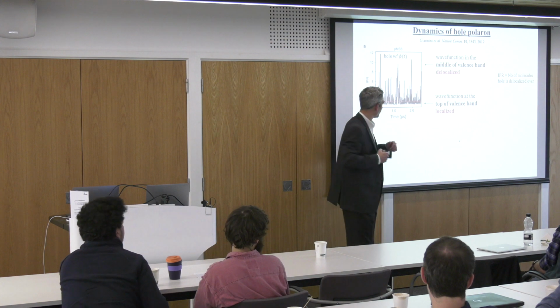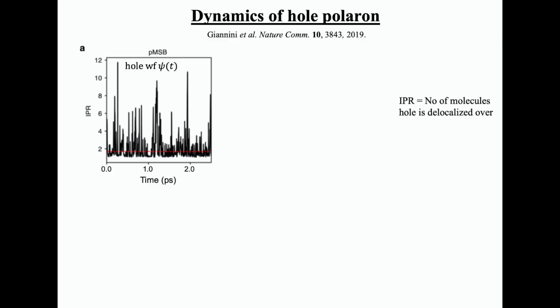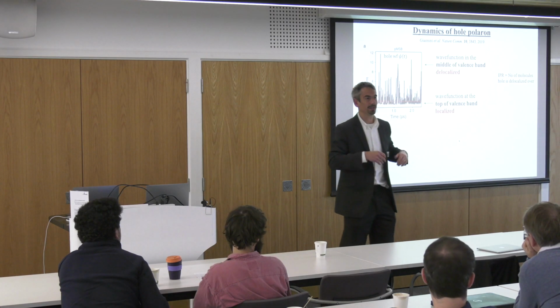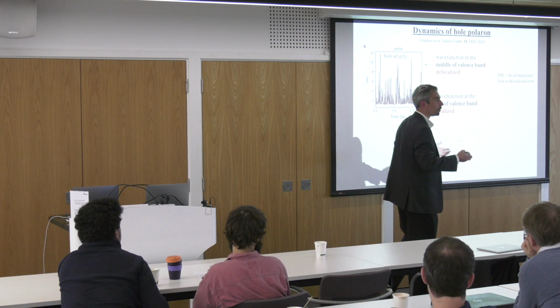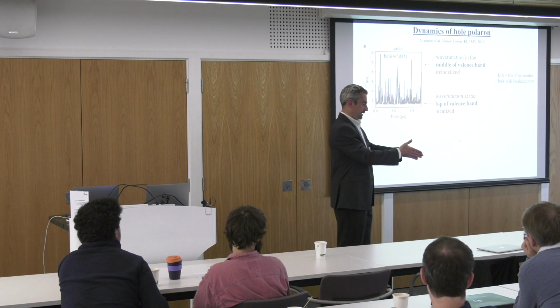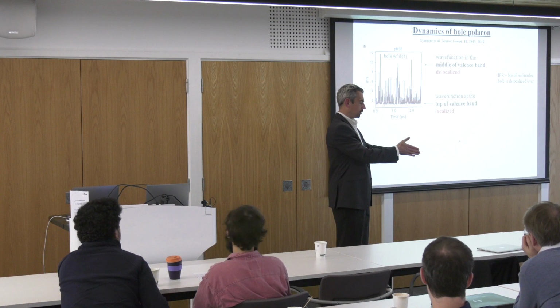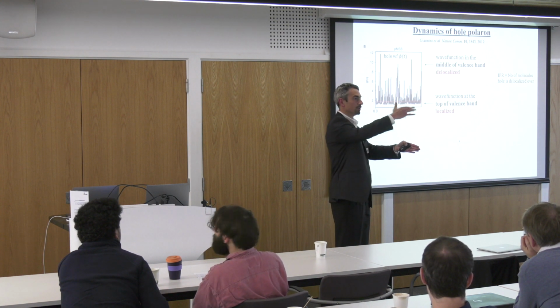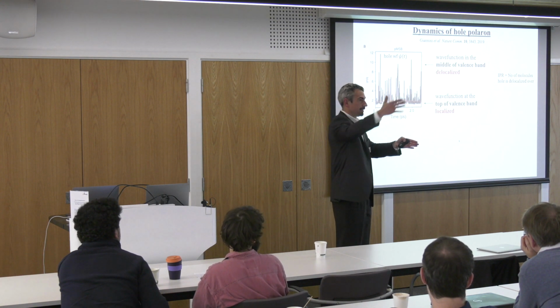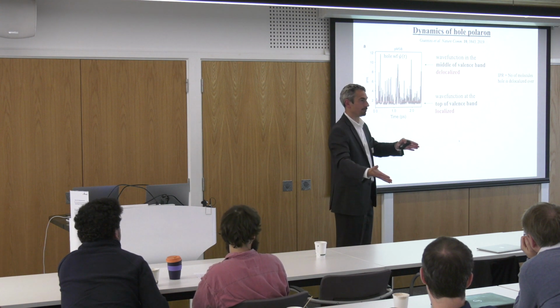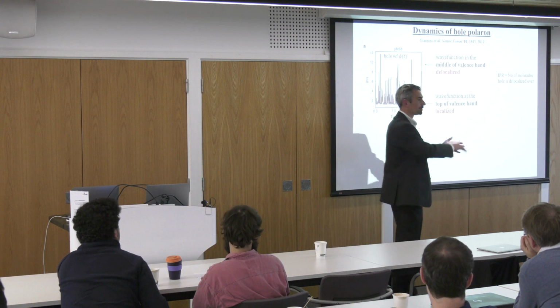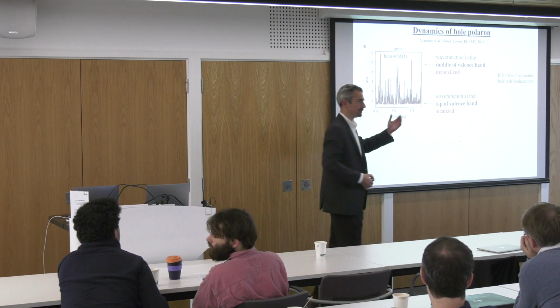of energy levels, so this would be the top of the valence band, its whole transfer. So these states would be at the top of the valence band, and these states here, the more delocalized one, are sort of somewhere close in the middle of the valence band. Now this is what we know is happening. The states at the top tend to be localized. The ones in the middle tend to be more delocalized, and the ones at much higher energy again become more localized. Okay? But the ones at very high energy are thermally not accessible.